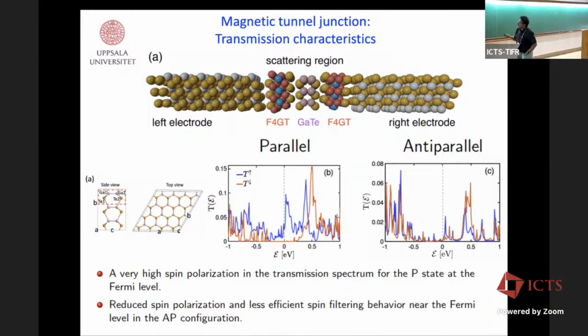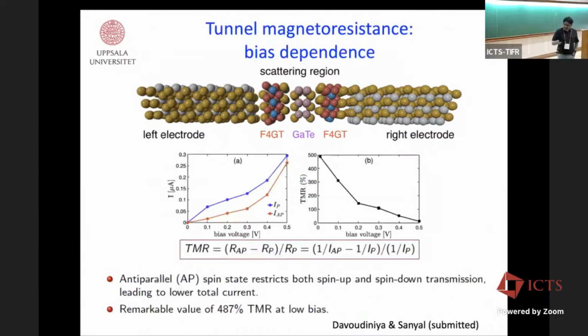So what you see here is the spin polarized transmission for the parallel and anti-parallel arrangement. The spin polarized transmission for spin up is very high, spin down is almost zero here, whereas for the anti-parallel, they are very close to each other. Now this is okay, but the actual quantity of interest is the tunneling magnetoresistance. For that, you need to calculate the current. You turn on the bias voltage and calculate the current for both spin channels and for both the parallel and anti-parallel configurations. That is how the currents look in these two configurations. And from there, you can calculate the tunneling magnetoresistance. As a function of bias voltage, you see that it goes down, but at a very low bias, the value is rather high, close to 500% TMR. So it looks promising, but I don't know whether it will be feasible in experiment or not.